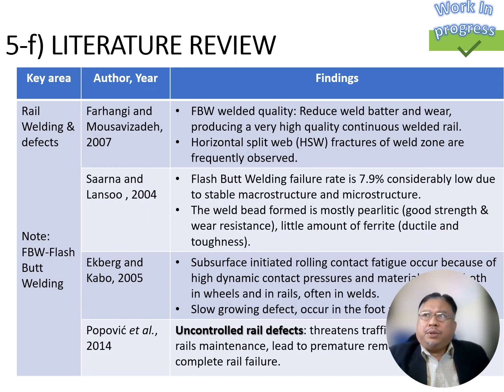On the literature review, there are many references in relation to the defects of welded rail and surface crack initiation. Farhangi and Mousavizadeh, 2007 concluded that even though flash butt weld is superior in quality compared to aluminothermal welding, the flash butt weld still has failure issues due to horizontal split web. According to Saarna and Lansoo, even though the flash butt weld failure is low at 7.9%, most studies found that delaying surface crack removal will cause the crack to propagate and continue to cause the rail break.